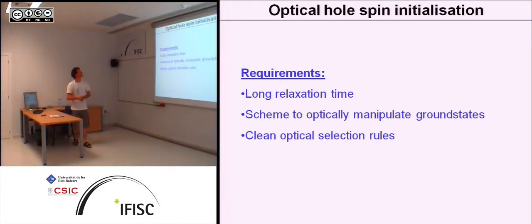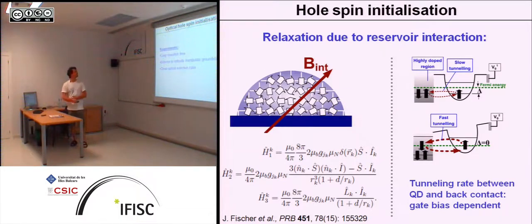Okay, so to optically initialise a hole spin, what you need first is long relaxation times, because you want the hole spin to stay in your intended state as long as possible. The next is that we want to do that all optically, so we need a scheme which allows us to optically manipulate the hole spin, spin up or spin down. And the other is that we need clean optical selection rules for this, because if you cannot address one state directly and unambiguously, then the whole experiment will be mixed up.